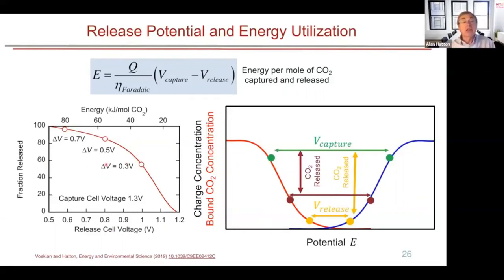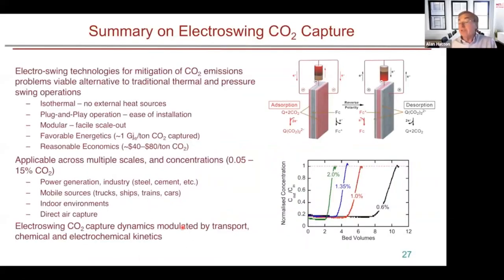So this is very, very encouraging, and it all depends on how much of the capacity of the quinones we want to utilize as to what the energetics per CO2 would be. And indeed, if you look at the overall summary of these systems, they are electro swing, and isothermal. There's no external heat source. They are plug and play, and can be really easily installed. They're readily scalable, and can be used at small scale and large scale with ease. The favorable energetics are about a gigajoule electric per ton of CO2, and reasonable economics, which we estimated at 40 to 80 dollars per ton of CO2. This is actually for direct air capture.